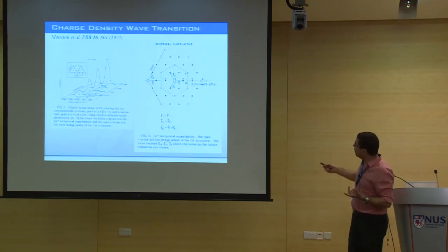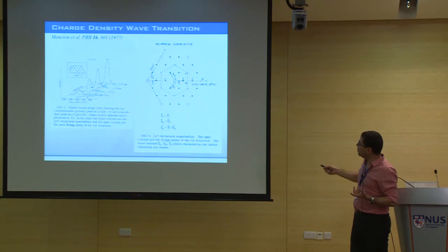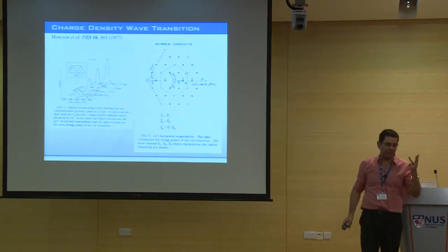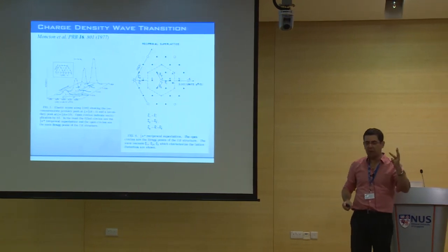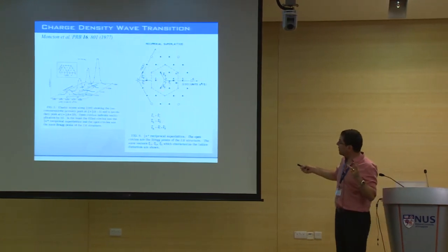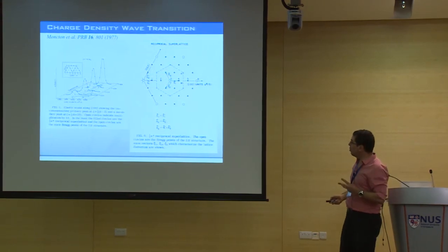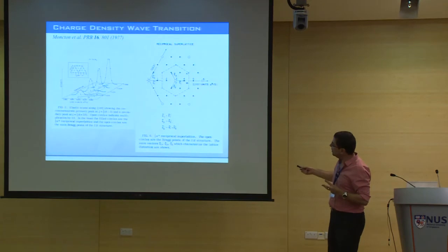And this is the original Brillouin zone, it's hexagonal. And then you have these extra peaks here, meaning that you have a triple charge density wave. So it has 3 different wave vectors oriented at 120 degrees from each other. Okay? So you can see the intensity of these peaks was very well characterized.